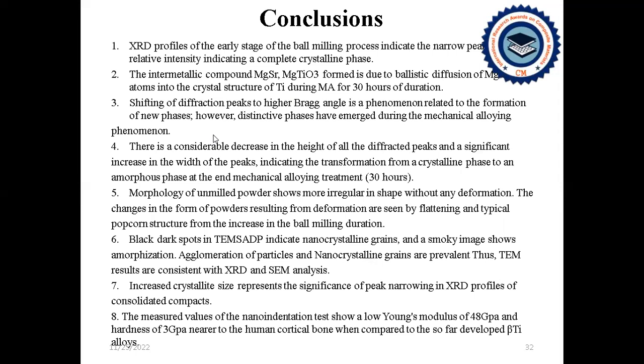However, distinctive phases have emerged during the ball milling, which suggests that it is because of the severe plastic deformation that occurs during the ball milling process, which helps the distinct phases to emerge as a result of mechanical alloying. And also the morphology, from the SEM and TEM study, of the powder shows irregular shapes without any deformation, and the changes in the form of the powder are due to the deformation, seen by the flattening and typical popcorn structure with the increase in ball milling duration. And the black dark spots in the SADP image indicate nanocrystalline grains,